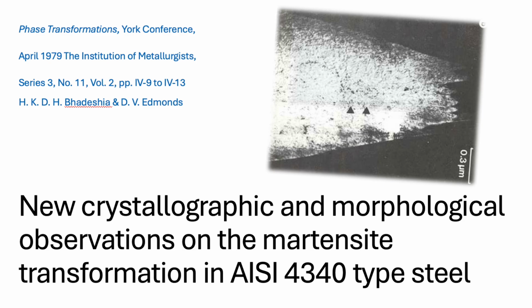And when a plate does form, you mentioned earlier, it's trying to minimize elastic strain energy. How does its structure help with that, especially at the tip? Right. Nature always seeks the lowest energy state. Plate formation, particularly when it happens at the higher end of the martensite transformation temperature range, needs to minimize that strain energy cost. The sources talk about the plate tip showing degenerate behavior.